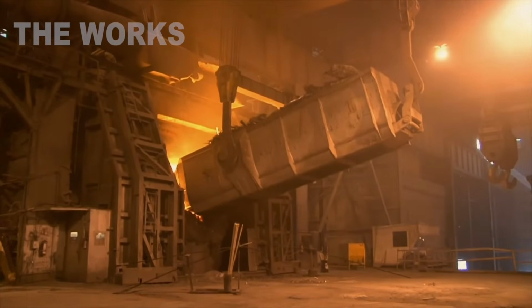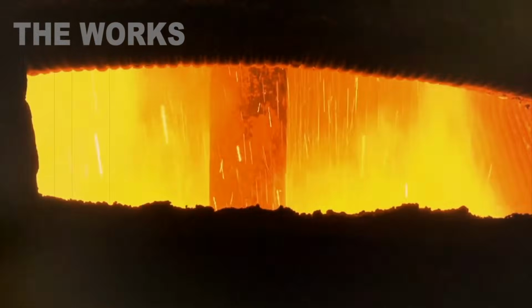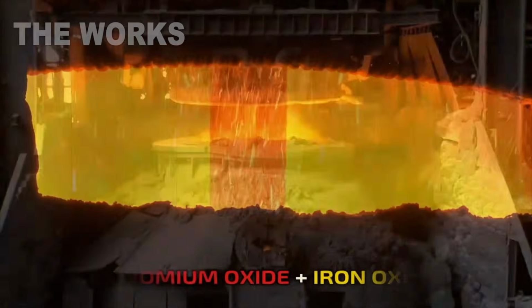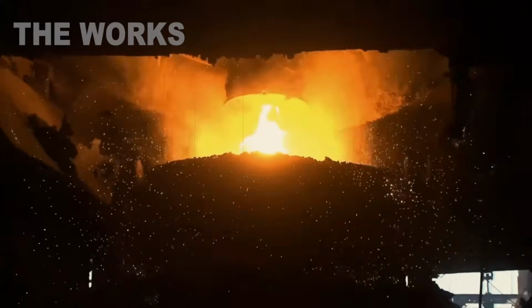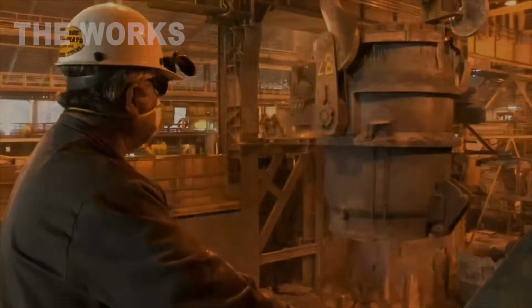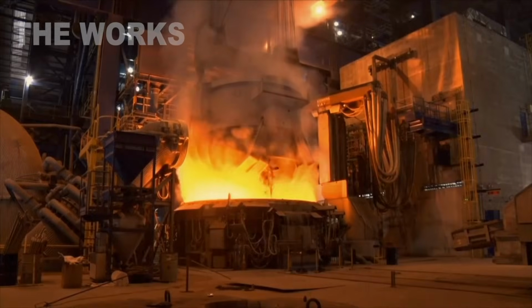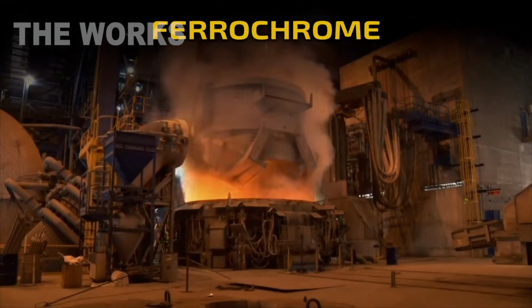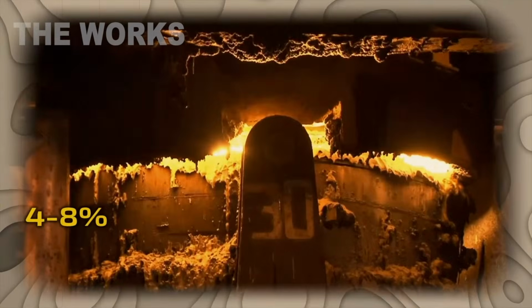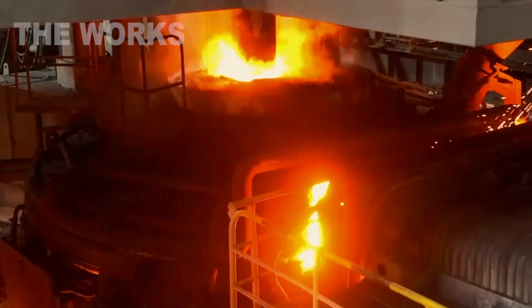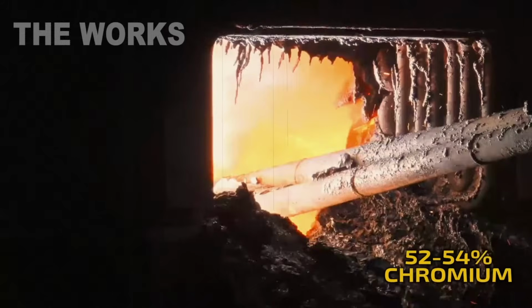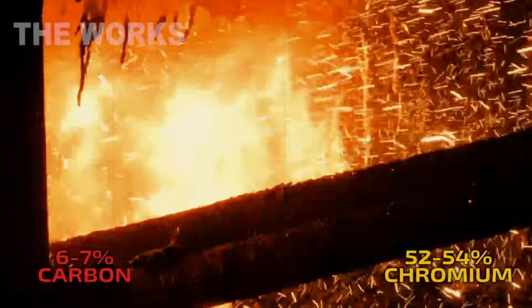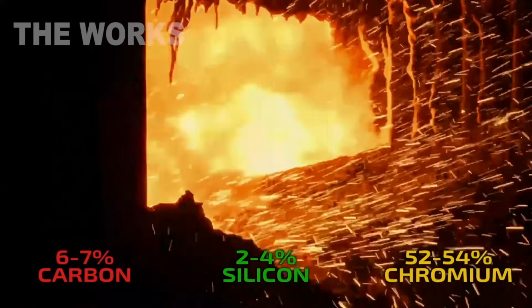Inside the furnace, complex chemical reactions take place. Carbon from the coke combines with oxygen from chromium and iron oxides, forming carbon monoxide that rises upward. Chromium and iron are reduced to their metallic state and fuse together, forming ferrochrome. Some of the carbon dissolves into the metal, producing high-carbon ferrochrome with a carbon content of 4 to 8%. Typical South African ferrochrome contains 52 to 54% chromium, 6 to 7% carbon, and 2 to 4% silicon. Ores from Zimbabwe with a higher chromium to iron ratio yield a product with 63 to 67% chromium.